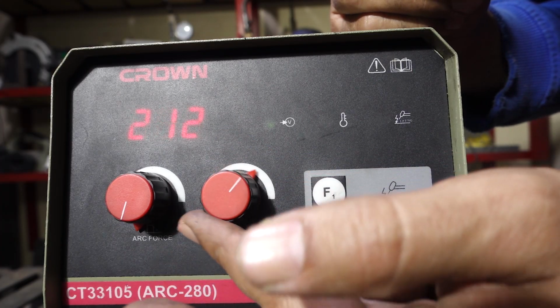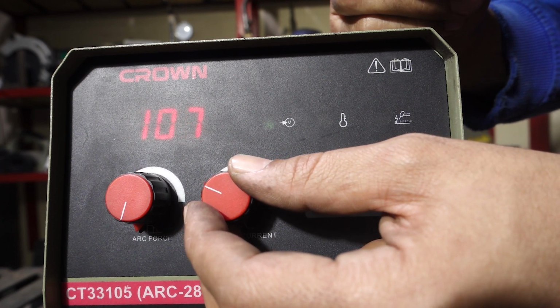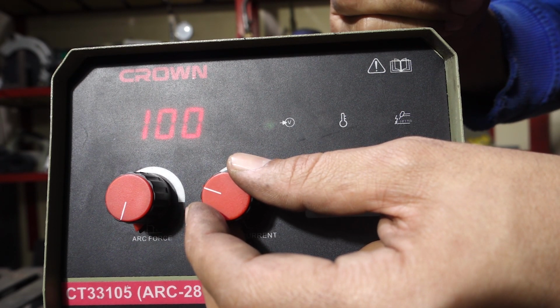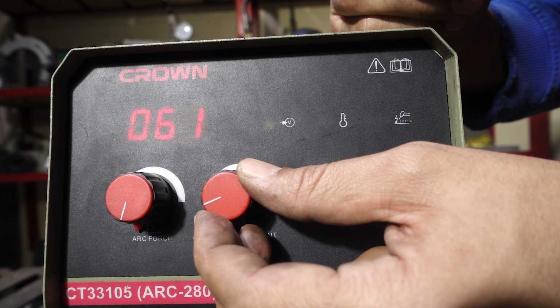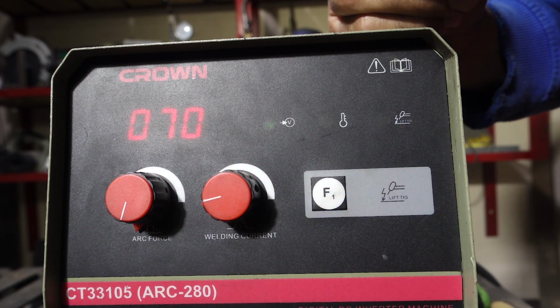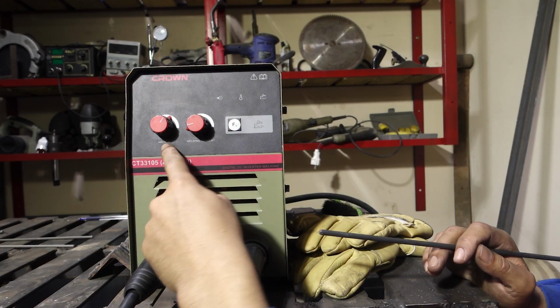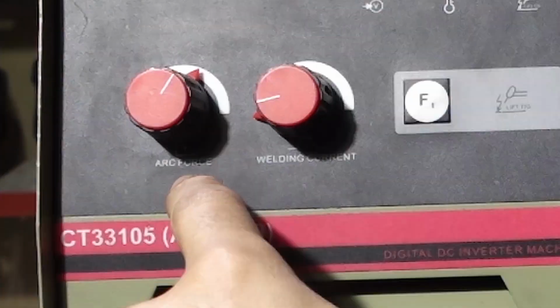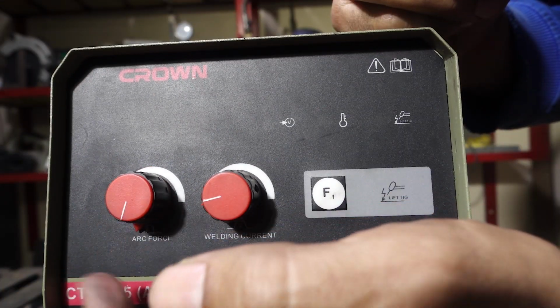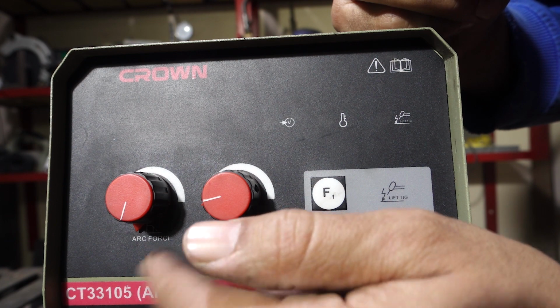This machine can weld up to 280 amps, and the electrode can weld well from 60 to 100 amps. I will use it at 70 amps. If I change it, I will tell you. And to who has this knob on their welders, because it is not on all of them, dial it back as low as you can. It is for the arc force and we don't need it here.